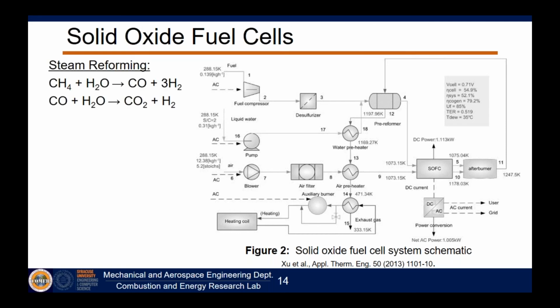We can also use butane in a very similar reaction, or propane, much higher hydrocarbons. And going through this steam reforming reaction, we can actually form syngas. We can then utilize that hydrogen directly and supply that to the fuel cell. So this is typical. Steam reforming is very common in solid oxide fuel cell systems. We then will combust, and usually any remaining fuel that's left over, supplying that heat for all the heat exchangers.